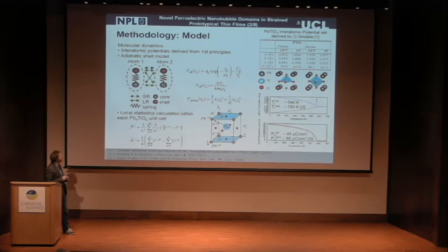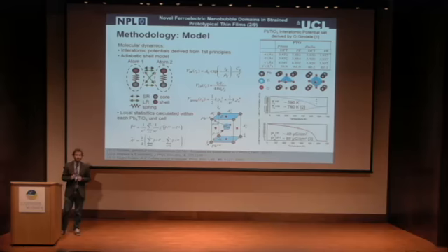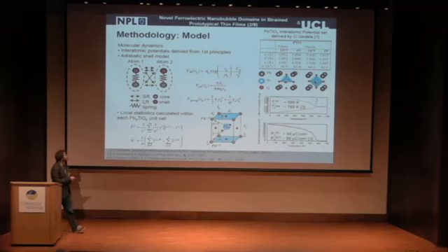It uses molecular dynamics. Here we set up our system of atoms and evolve it using classical Newtonian mechanics. Obviously our particles are interacting. We represent our short-range interactions through this Buckingham potential here, which favours the short-range, centrosymmetric, high symmetry configurations. Then we've got charged particles, so we've got this Coulomb interaction. And then also, because we're dealing with ferroelectrics, obviously we want this intrinsic polarization. How do we model that if we've got particles? Well, basically we split it up into three components. We represent the nucleus as a massive core, we represent the electron density as a spherical shell, and then we tether the two by a spring.